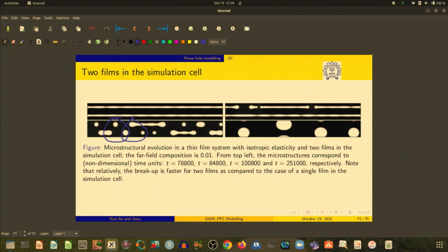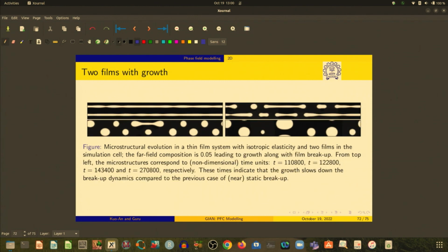If you have 2 peaks in this film and in between that the other film peaks, that is because of elastic interaction between films. So, the films can sense the other one. So, if it peaks here, then that film will have a trough there. So, it will have a peak in between where these two have a trough and so on. So, they adjust themselves, and that is what leads to this very clearly seen triangular structure that you see here. Okay, this is coming because of the elastic interaction between the films. So, you can study these kind of things in the simulation.